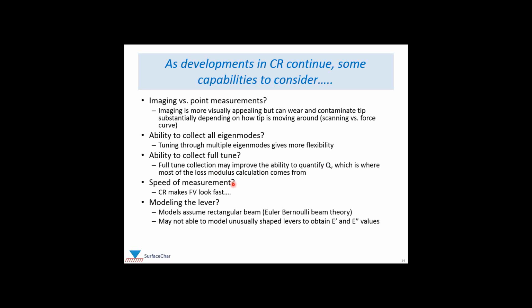Speed, contact resonance can be very, very slow. Sometimes it makes force volume look fast. So that's also been an area of improvement. And finally, the ability to model the lever. Currently the models assume rectangular beams for the levers. So levers that are unusually shaped, you might not be able to do the calculation all the way to storage and loss modulus if it's an unusually shaped lever that does not follow Euler-Bernoulli beam theory.